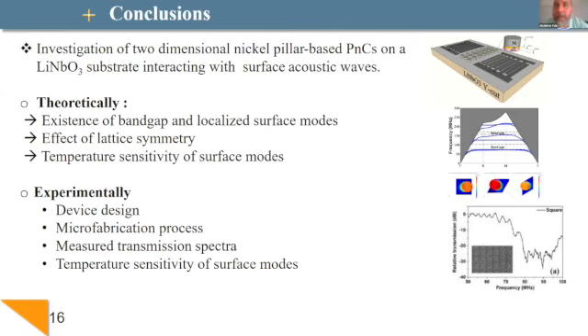Yeah, it means the crystallographic cut, the face of the niobate. We introduce all the crystallographic properties of lithium niobate. The properties are defined in a tensor, and we just rotate the tensor to get the rotation, a simple rotation of the matrix.